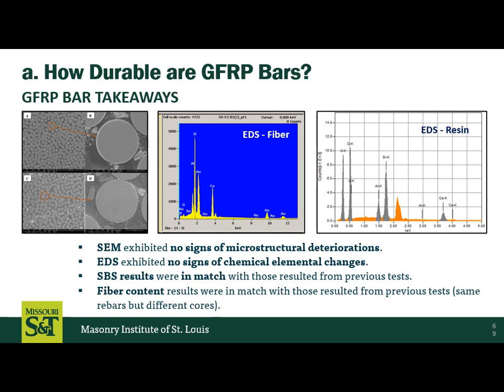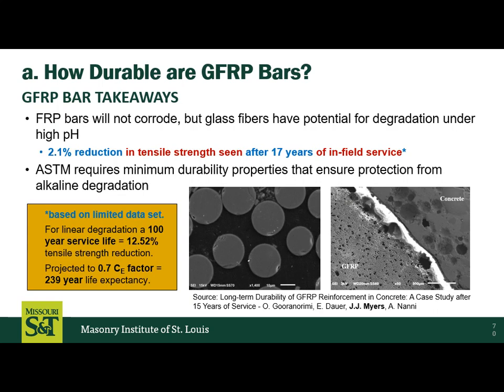So this figure on the left here, each of these dots is the fiber. When we zoom in, you can look at the fibers, see if there's cracks in it. You can look at the resin, which is the glue around the fibers, to see if there's any problems there. We also do EDS on the fiber, EDS on the resin. We can compare those imaging to pristine bars to see if there's anything that looks abnormal. Takeaway is it was performing really great.